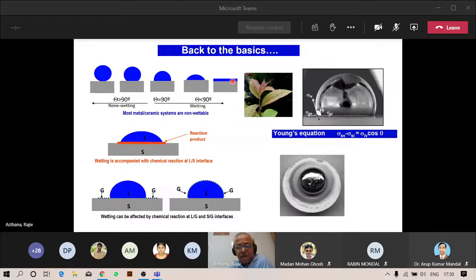And if you want spreading to take place, like a brazed layer to spread out, you want this angle to be nearly zero. Of course, in some applications, you don't want wetting. For example, in melting crucibles, in foundry work, you don't want the liquid metal to wet the surface of the crucible. But for the application that we are looking at, joining, a low contact angle is important. One interesting thing here is that in a non-reactive low temperature system, like an organic liquid on a solid surface or even water on a glass slide, water will take just a fraction of a second, a few milliseconds maybe, to spread out to an equilibrium shape.